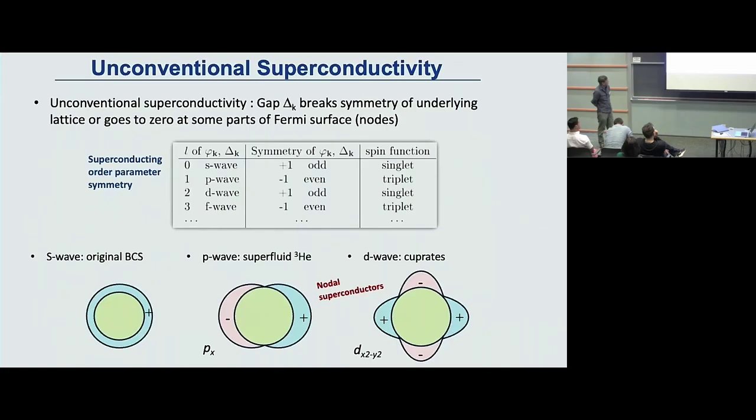Another signature of unusual superconductivity is measuring the pairing symmetry, which was already discussed, using various interferometry methods. In fact, it is one way to pin down the d-waveness of the superconductor. It's a little bit hard in 2D superconductors in general, not only Moiré superconductivity, because the magnetic penetration length is long. So controlling this with SQUID-type devices and corner junctions does not work too well compared with 3D superconductors.